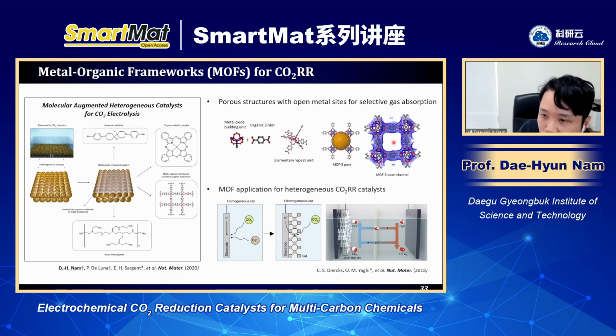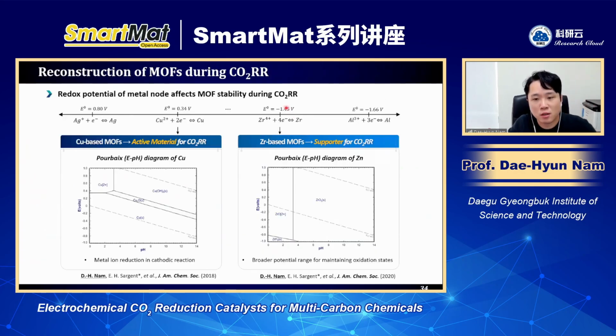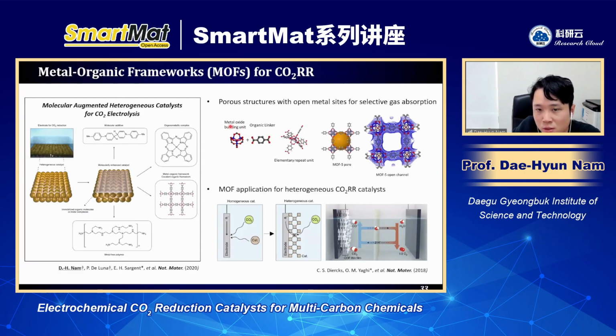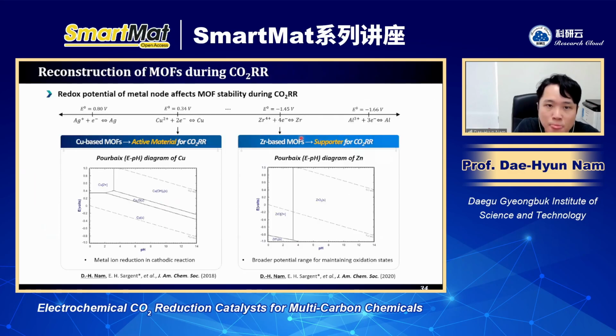But what I found in MOFs is that MOF stability is also related to the reconstruction, which I introduced previously. I'm going to explain this in more detail. A MOF is composed of a metal center and an organic linker, and we can categorize MOFs according to the metal center. I found that the oxidation tendency of the metal in MOFs is very important to understand the reconstruction of the MOF. For example, we can have a copper-based MOF, and also a zirconium-based MOF. Their oxidation tendency can be understood by the reduction potential, and we can also get the information from the Pourbaix diagram.